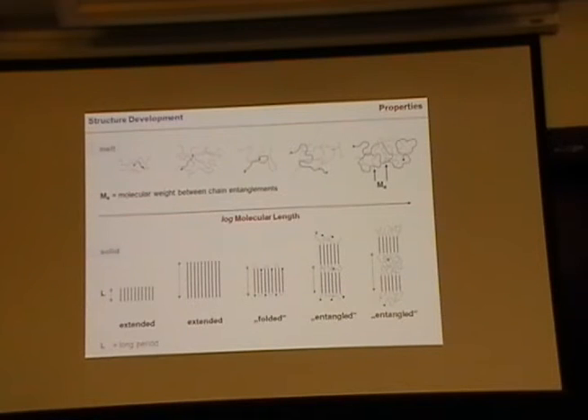How can we measure Me? Me, I will show that. One is, actually it's a good question. We do it usually indirectly. So it's really viscosity. So when we know we have one entanglement or three, I show some examples of mechanical tests, where we start to have plastic deformation. We know we have these three entanglements, so we have a network. We know usually the molecular weight, so the total one, and simply divide it by three.